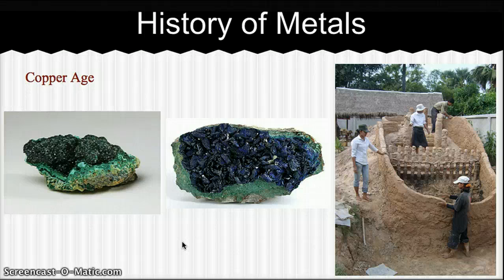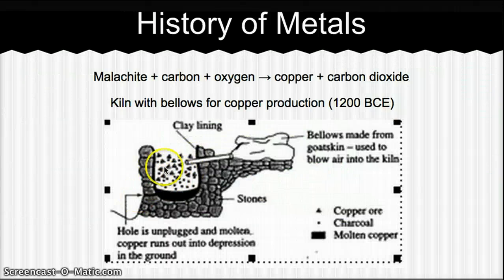Now, the earliest metalsmiths crushed the copper ore and mixed it with charcoal. Air was blown into the furnace to raise the temperature. The ore was rich in silica or quartz, and in the smelting, this silica melted to form a glassy slag containing copper grains. Later, metalsmiths learned that by adding iron ore to the furnace, the copper could be more readily recovered from within the iron silica slag.